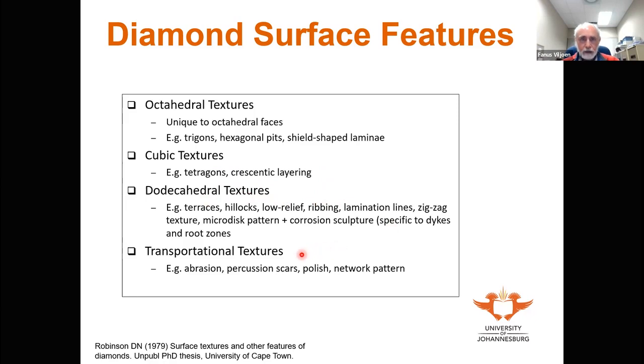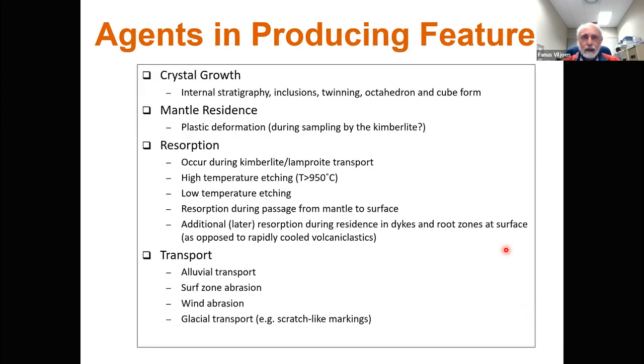And then finally, if diamonds are released from the kimberlite during weathering and they end up in the surface environment, you may see things like abrasion, percussion scars, polish, and network patterns, for instance. So what are the agents in producing surface features? Well, first of all, diamond growth, crystal growth would be an agent in producing surface features because we can see the internal stratigraphy.